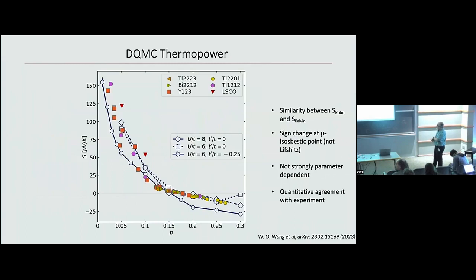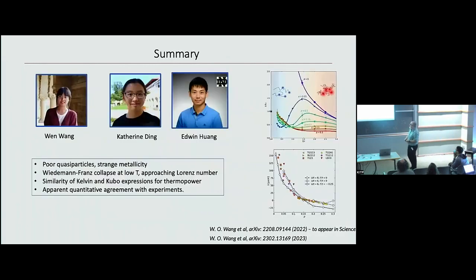And then if we overlay the experimental values for these 6 samples, along with the calculation for different values of U or different values of T prime, all we have to do is translate our hopping in terms of a temperature. There's nothing else that we do. Not only does this give good qualitative agreement with the doping dependence, but quantitatively it's in pretty good shape. So I think I've taken all of my time. I'll leave my summary up there, and thank you very much.